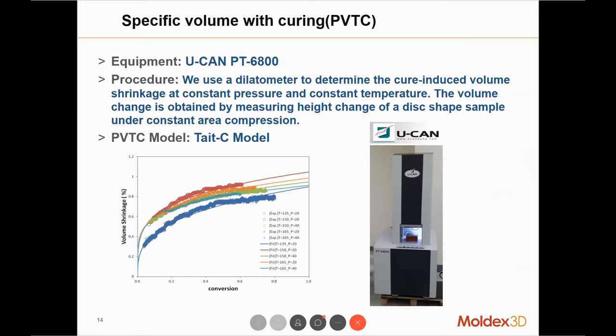And then when we go to the curing stage, we have to consider the PVT. So pretty much like a thermoplastic during the packing stage, the PVT curve basically dominates the whole process. For the curing stage, PVT for curing is one of the most important properties that we need to consider. So we'll use the PT6800 machine from U-CAN to measure the PVT, very similar to the way we measure PVT for thermoplastic. The polymer will be put in the chamber, and the area of the chamber remains the same. Only the height of the polymer will change.